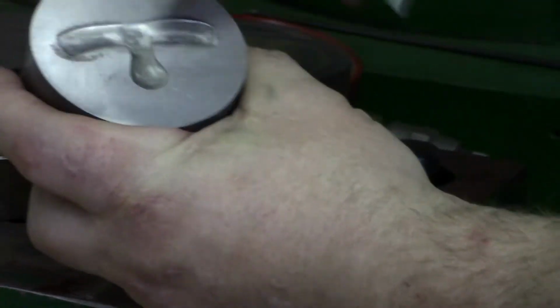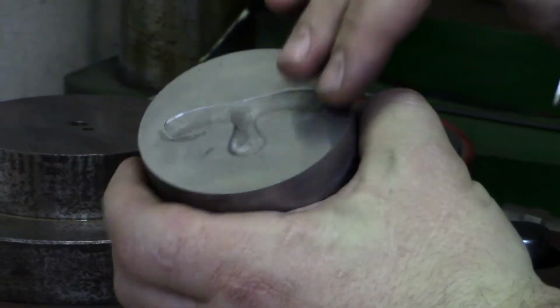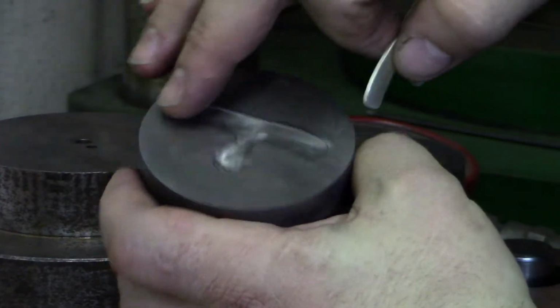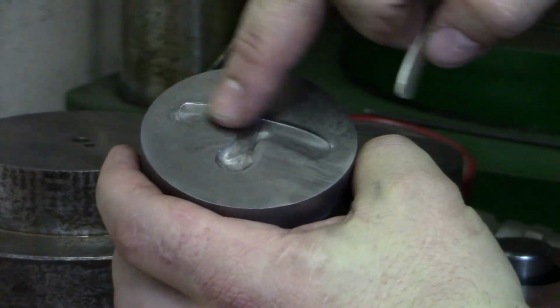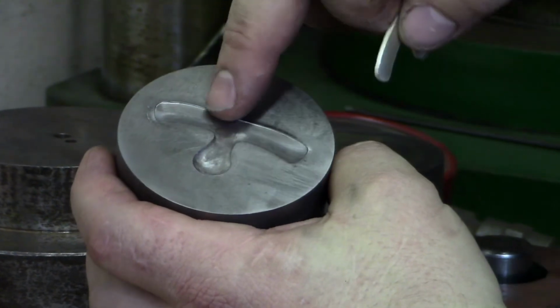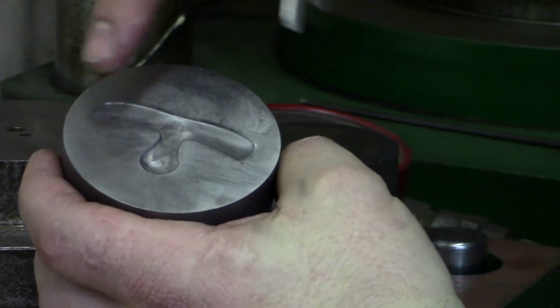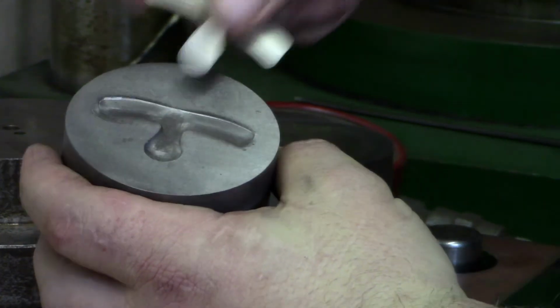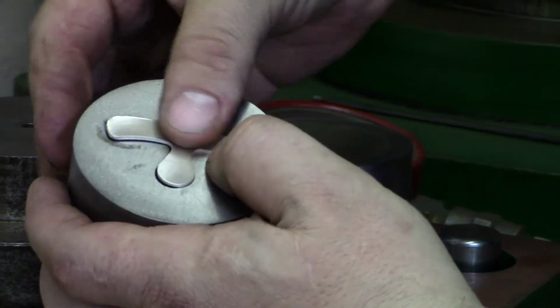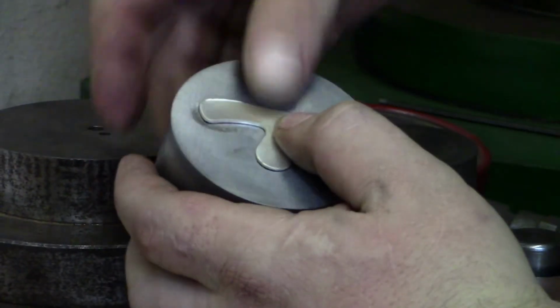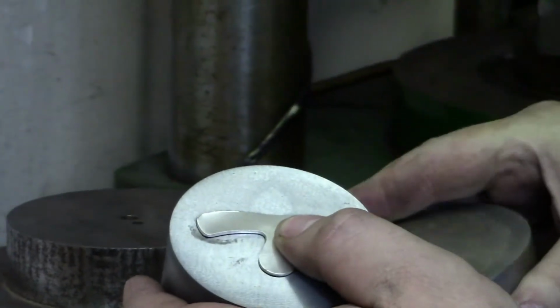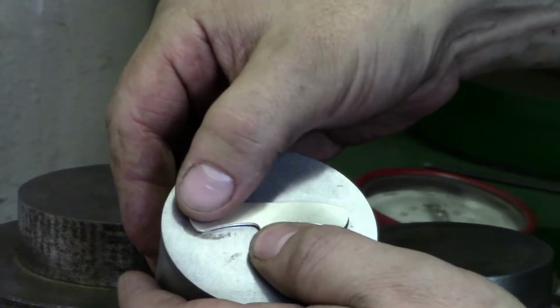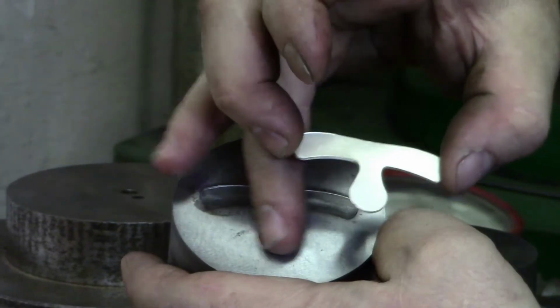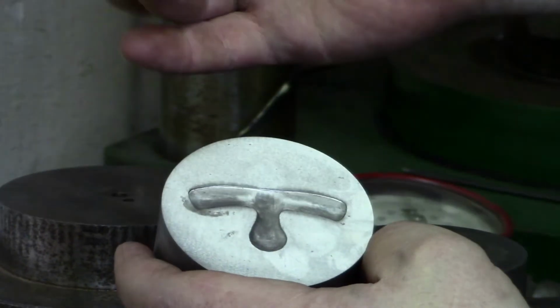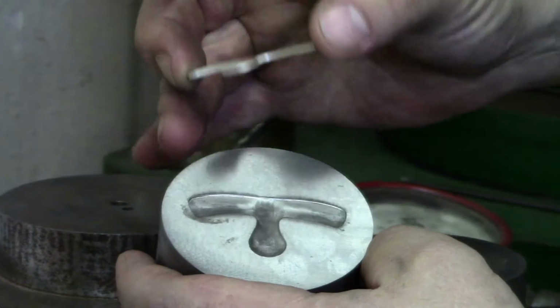So what we're doing is we're taking this blank that we took out of the punch press, and we have a forming die that this might not transfer or be able to be seen that well on the camera, but it's already got some of the pre-shaped form in there where I was just speaking about, where the blade is thicker than the band itself. It aligns in there. It has the same exact orientation as the blank, and we're actually just going to hit that with a flat die. What it's going to do is thin the band out while leaving the thickness of that blank, and start to put the bulb, what I would call the bulb, on the paddle of